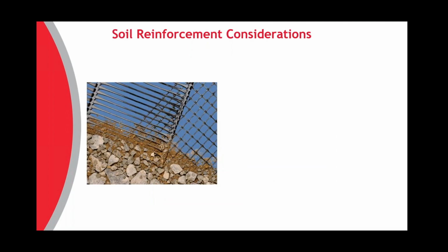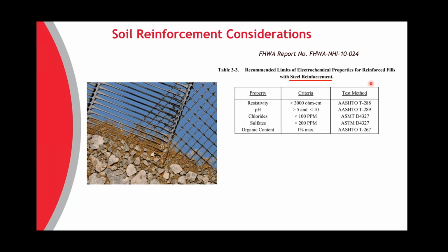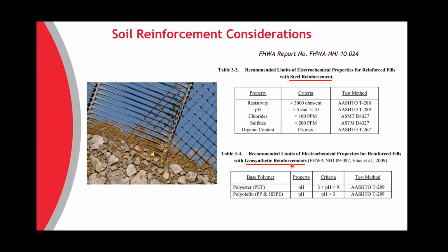So let's switch gears now and look at soil reinforcement considerations. FHWA has put forth these recommended values for electrochemical properties. You have to be concerned with erosion or degradation of steel reinforcement in structures. You have resistivity values, pH 5 to 10, chloride, sulfates, and organic contents. However, if you use geosynthetic reinforcements, about the only concern you have is pH values. You don't have to worry about erosion or degradation of these materials due to electrochemical properties.